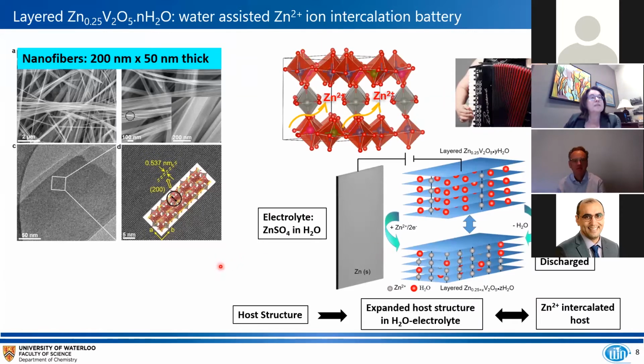So our adventures in this were not in zinc air batteries or zinc bromide batteries or others, but we tried to develop an intercalation battery that was similar in its function to a normal lithium ion cell, where there is intercalation of lithium ions in and out of the positive electrode. And we did this by creating nanofibers of these layered vanadium oxides. It actually has a little zinc in it to start, but it has this vanadium oxide sheet structure that is shown here with just a few zinc ions between the layers. And the point here is that these nanofibers are very thin and very long. So they have a very high aspect ratio. And they're only about 200 nanometers wide by about 50 nanometers thick.